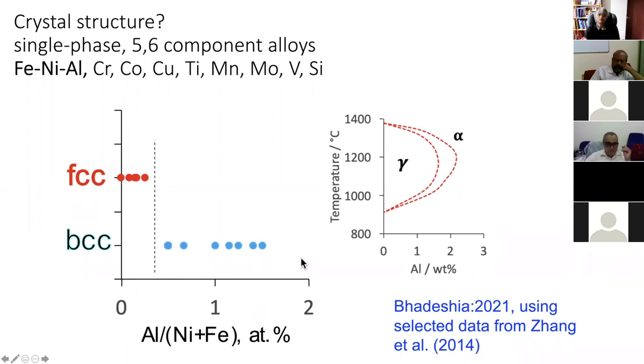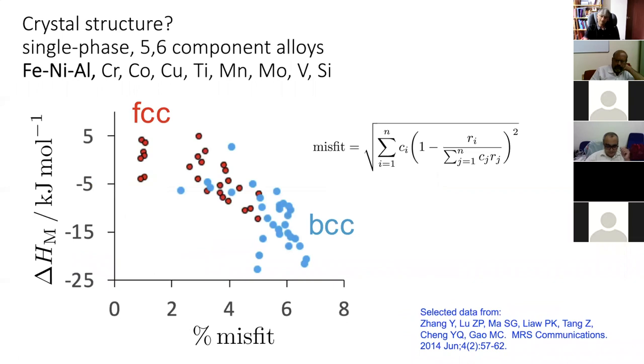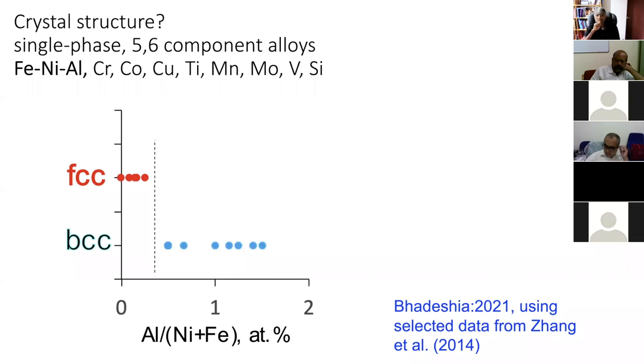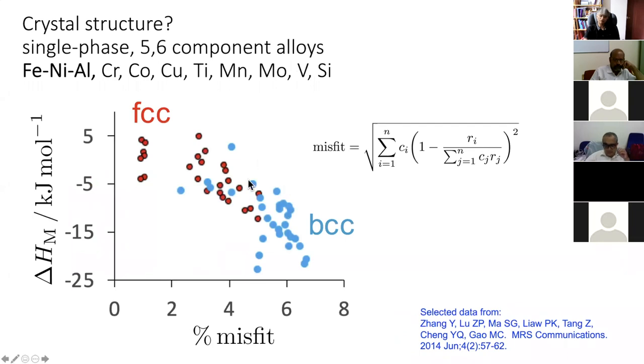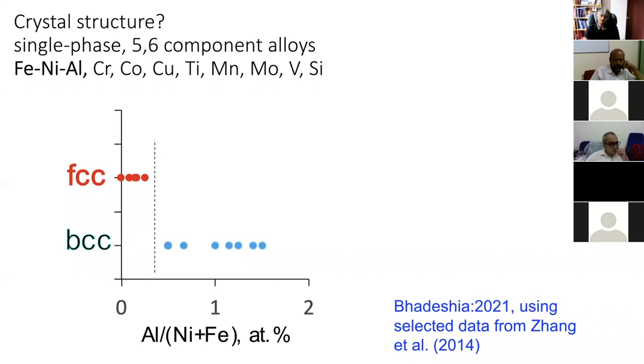Okay? And that turns out to be the case for this very large number of high entropy alloys which contain all of these elements, and I'm completely ignoring this. Okay? So you could use this when you're talking about a combination of these elements to see whether you end up with FCC or BCC. Such a simple calculation. Now, of course, in preparing these lectures, I find some anomalies, such as this overlap region. And this seems to indicate something important, that I can't ignore the other elements.